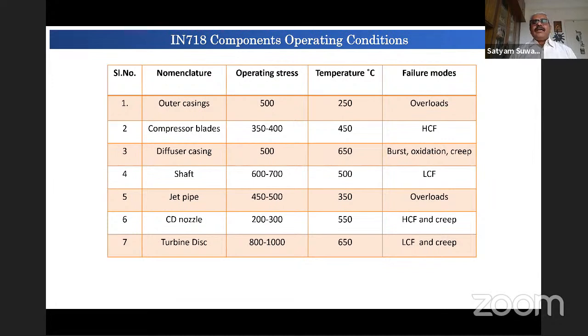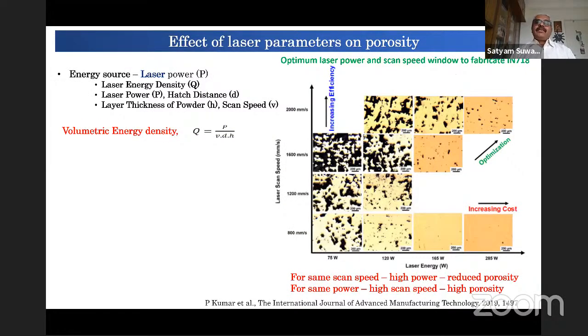Gas turbine engine, and one can see that the maximum temperature is up to 650 °C, for which Inconel 718 qualifies quite well for operating under these conditions. Now, the main problem is related to the manufacturing of these components.